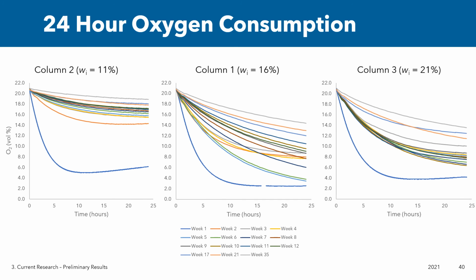During the time the oxygen cap is on, the change in the volume percent of oxygen in the headspace is monitored, which corresponds to sulfide oxidation, as it is an oxygen-consuming reaction. From these three graphs, it is evident that the first week, shown in blue, resulted in the most substantial decrease in oxygen. But what was unexpected was that the most unsaturated column, column 2, shows the least oxygen consumption overall, potentially indicating that oxidation reactions are not occurring to the same extent as they are in the wetter columns.